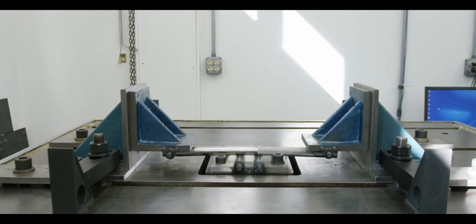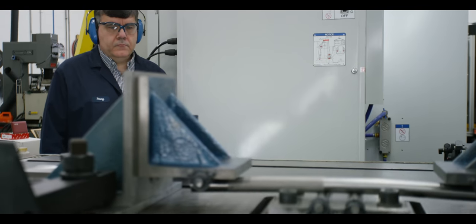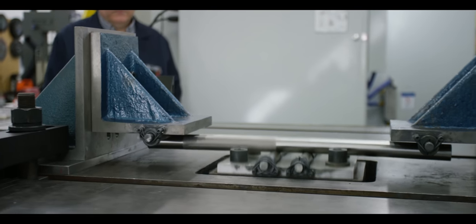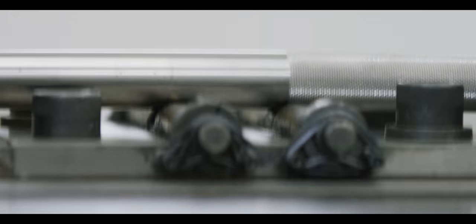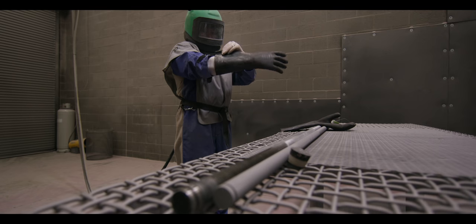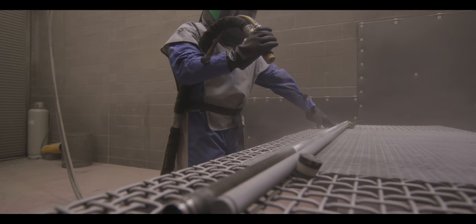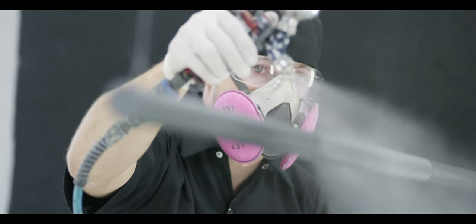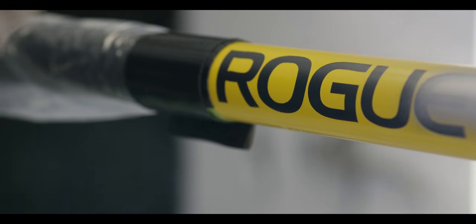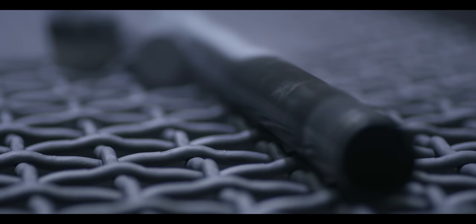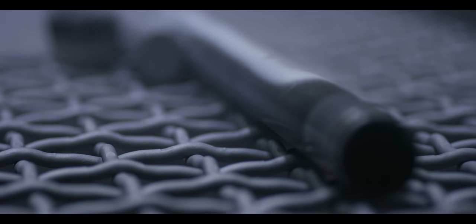The first thing we found was that chrome decreased the durable lifespan of a barbell shaft by up to 50%. It turned out that it didn't matter whether the chrome was from Europe, China, or the United States. It also didn't matter what type of seal or what the tensile strength was. In every case, it decreased the durable lifespan of the bar. We found that other coatings such as zinc or Cerakote did not negatively affect the durability of the barbell. Media blasting a barbell shaft to prepare it for Cerakote improved its performance in our test.